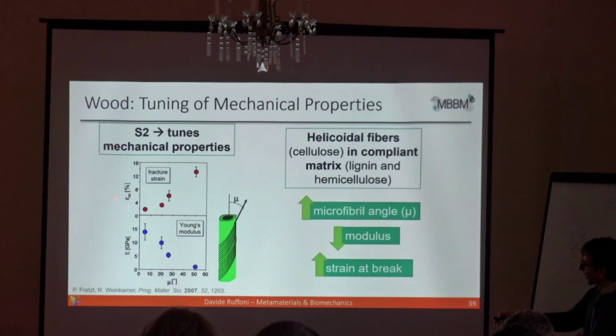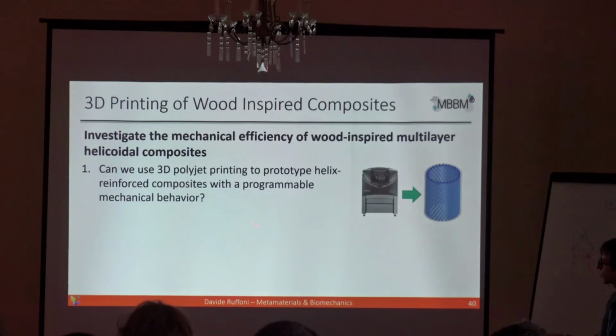And on the other side, the fracture strain has an opposite behavior. For a very small angle, fracture strain is small because cellulose molecules are brittle. And if you increase the angle, wood can reach higher fracture strain. And so there is a tuning, let's say, of the material behavior just by tuning this microfibril angle. And so we were interested to somehow reproduce this principle in synthetic materials.